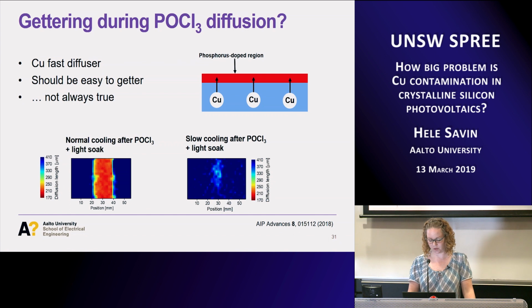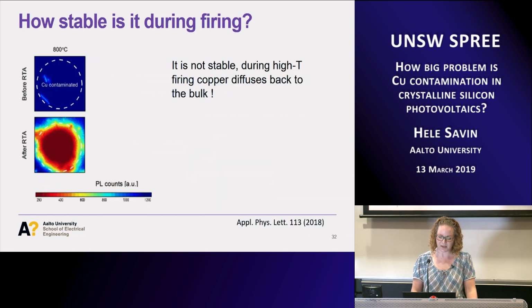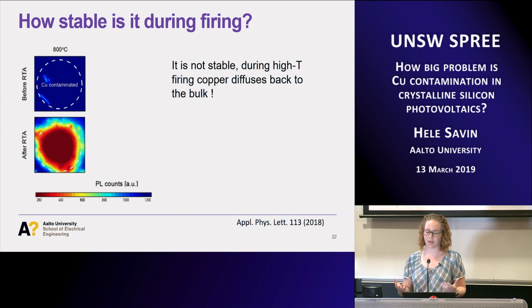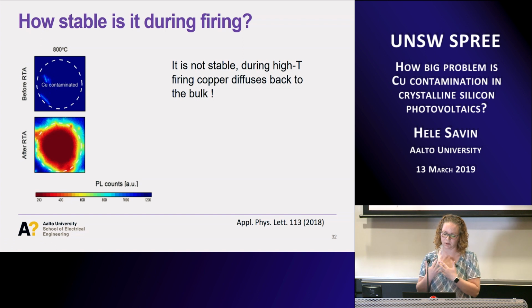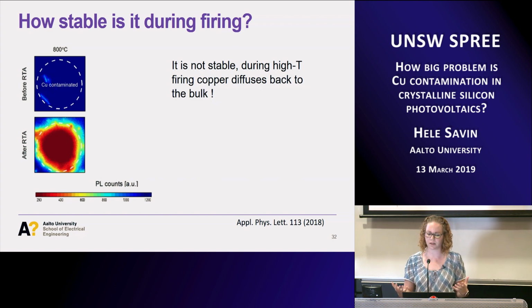Okay, but the POCl diffusion is not the final step in solar cells. The last step is the firing, which is a few seconds at a high temperature. So we did experiments in a firing furnace to study, okay, if we have gettered the copper to the emitter, what happens during the firing? So before firing and then doing the light soaking, we can see, yes, now we have gettered the copper there, but after we fire the samples, then we actually see again that the copper spots appear after light soaking. And it's not really surprising that this high temperature just pushes all your copper back to the bulk, and there you go, you have again the same problem.